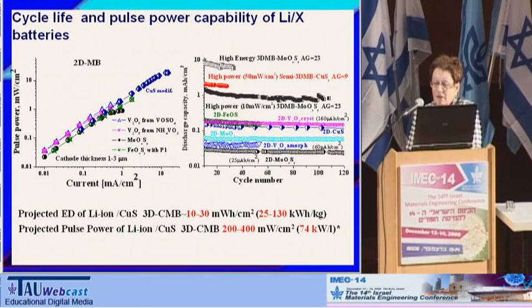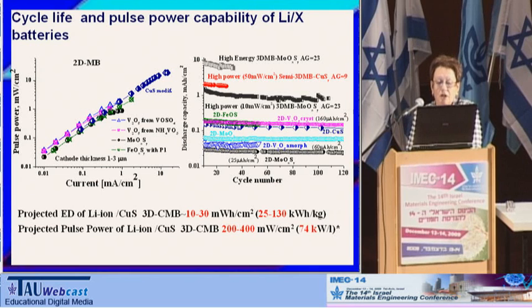with optimized nano-size electrode materials and area gain higher than 20, will be about 30 milliwatt hours per square centimeter. And the projected pulse power for this system will be something about 400 milliwatt per square centimeter.